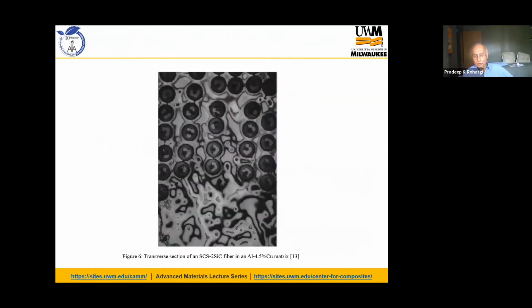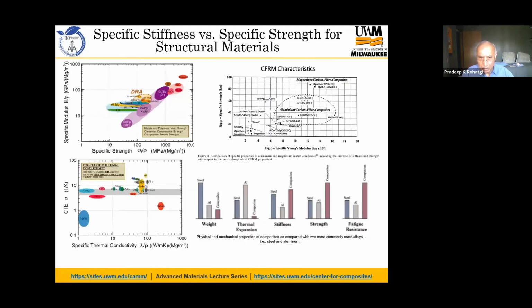Another effect of reinforcements on the solidification microstructure, this is an example where silicon carbide fibers, you are looking at the cross section, are embedded in an aluminum copper alloy. The bottom part shows where there are no fibers and the top part shows where there are fibers. And what this shows is that the micro segregation, shown by the gradation of black colors, is much less when there are particles present during solidification. So you influence nucleation, you influence growth, and you influence micro segregation in a casting when fibers or particles are present in the matrix, and this has implications on properties.